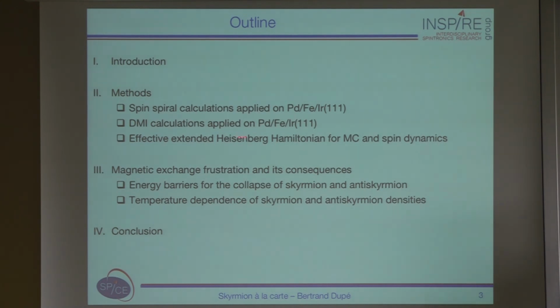We'll see that we can actually calculate from DFT the Dzyaloshinskii-Moriya interactions, and then based on these two steps, we can obtain an extended Heisenberg Hamiltonian that we can play with Monte Carlo and spin dynamics simulation. And then I will use this to focus on the magnetic exchange frustration and its consequences, where we will look at energy barriers for the collapse of these topologically protected spin structures, and also temperature dependence, so the B-T phase diagram.